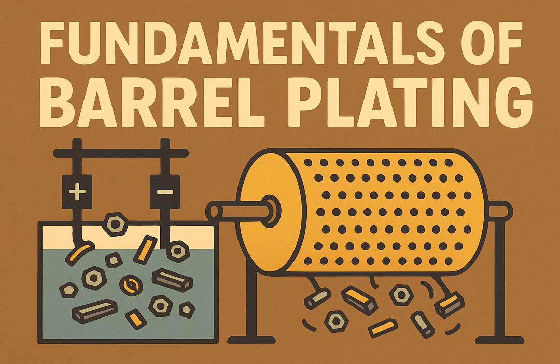It really is. If parts aren't perfectly clean before they enter the plating bath, you're almost guaranteed to have problems. They recommend pre-cleaning excessively oily parts separately to avoid contaminating the main cleaning baths too quickly. Techniques like electrocleaning and ultrasonic cleaning are mentioned as aids to ensure surfaces are truly clean. So if cleaning fails, what's the immediate consequence? What goes wrong? The most common and frustrating result of poor cleaning is adhesion issues, where the plated layer doesn't stick properly to the base metal and peels or blisters, just flakes right off.